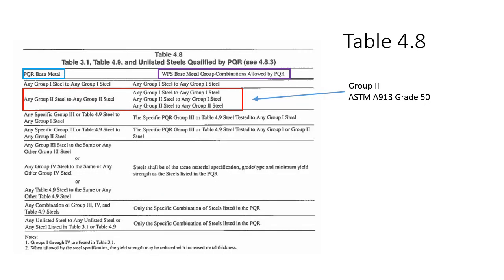Table 4.8 tells us what base metals we get if we qualify a procedure with a certain material. For this example, up there in the blue on the left hand, I've got PQR base metal. Let's say the PQR base metal is ASTM A913 grade 50, which is a group 2 steel from Table 3.1. So I qualify with that. I can weld any group 1 steel to any group 1 steel. I can weld any group 2 steel to any group 1 steel. And I can weld any group 2 steel to any group 2 steel.